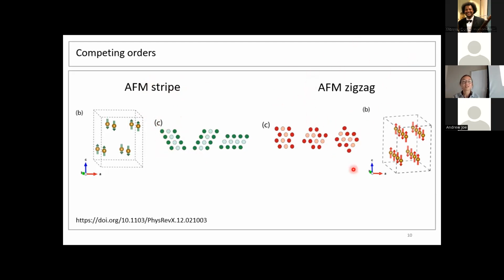and another one which is a zigzag. So there are two kinds of order, two kinds of patterns, and each of these has three orientations that it can take. The stripe can point in three different directions, the zigzag can point in three different directions. And it turns out that when we decrease the amount of iron just a little bit, the stripe will dominate. When we increase the amount of iron just a little bit, the zigzag will dominate. While when we have our really nice, perfect triangular lattice, they coexist.